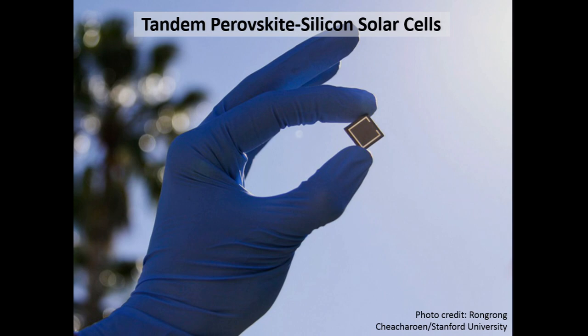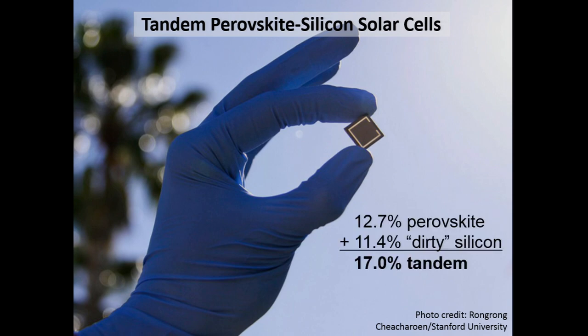You'll hear a bit more about the perovskites, methyl ammonium halide perovskites, in a bit. But this is a potentially very low cost material, thin film, wider band gap material that could complement silicon nicely. And some of the exciting results, perhaps coming from the bottom up in terms of efficiency, is if you are to combine a semi-transparent perovskite on the order of 12.7% with a very dirty silicon material, it's capable of achieving a 17.0% tandem, which is very interesting. This is in the range of commercial solar cells, right? So it's demonstrating the possibility of combining two potentially low-cost materials, a marriage of equals, and generating a tandem device that is capable of achieving a respectable commercial efficiency.